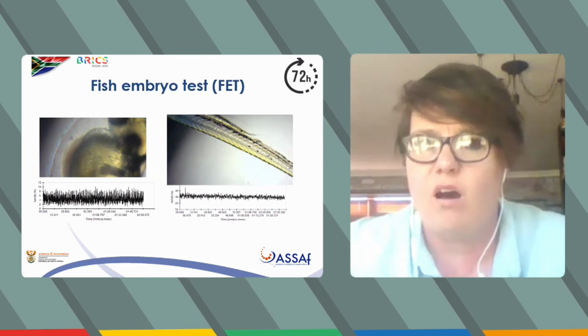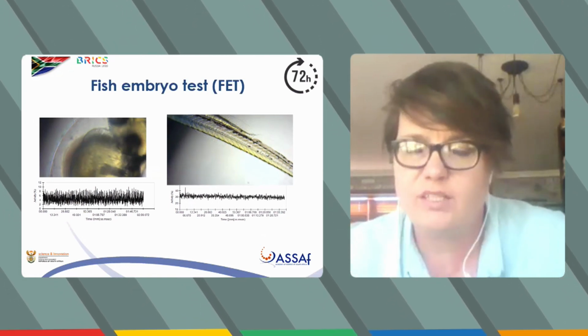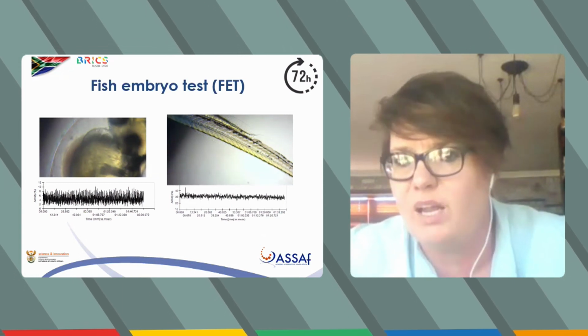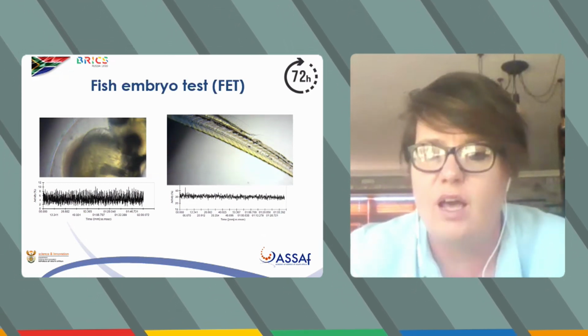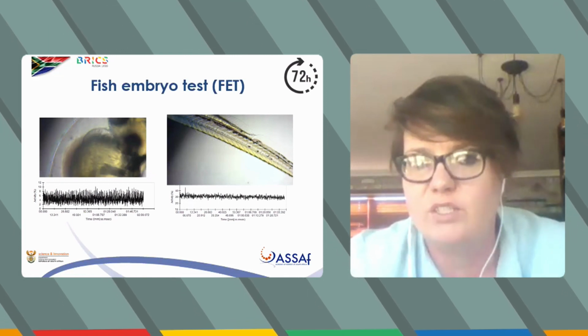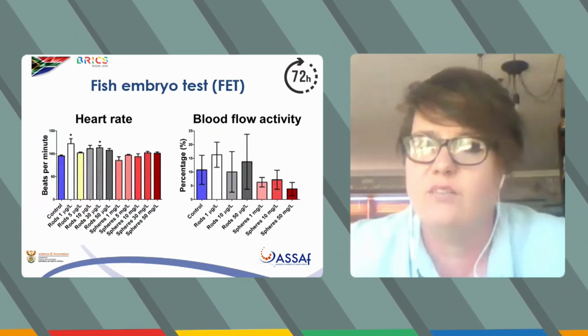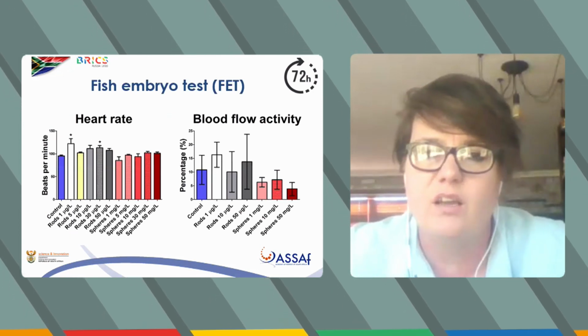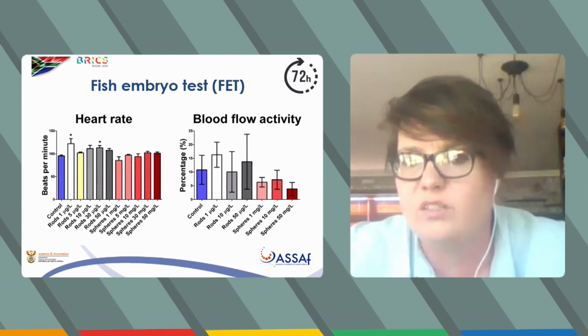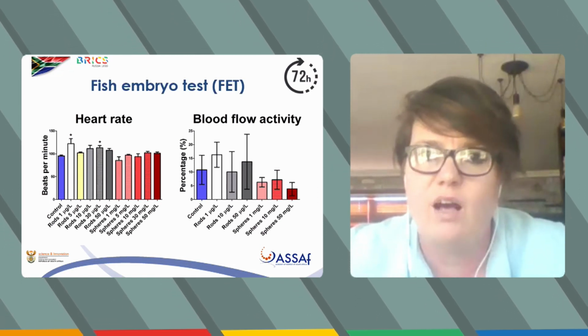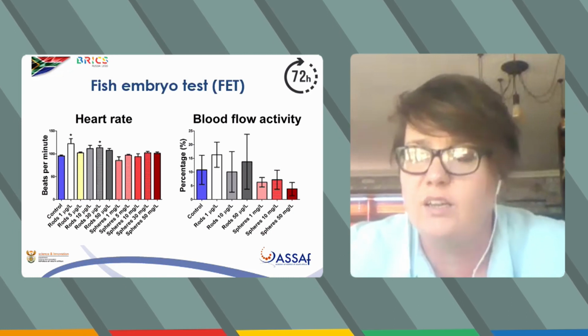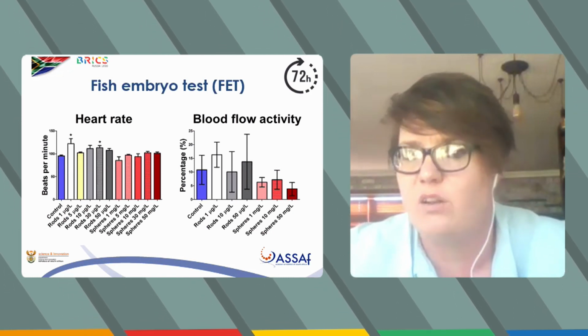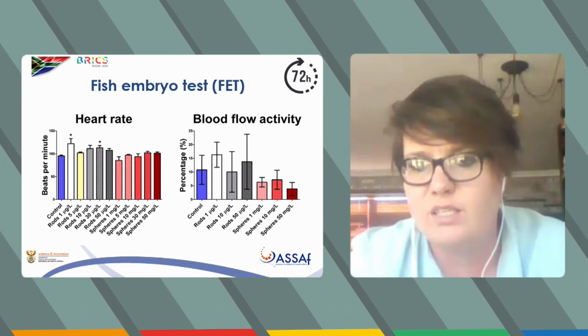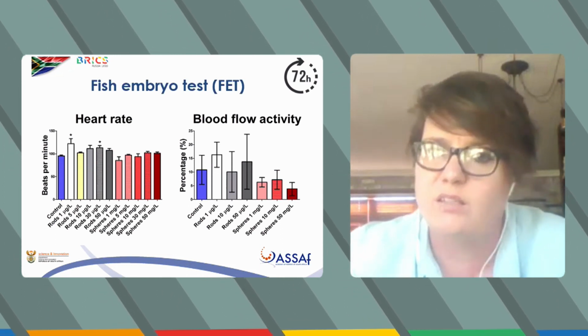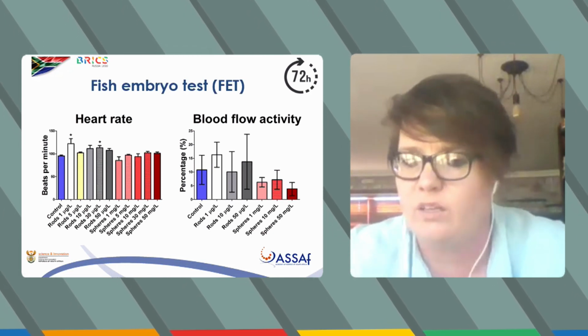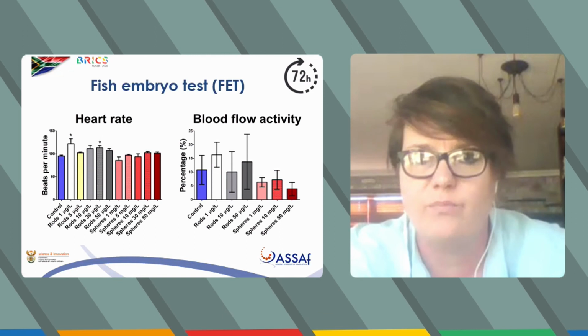When we look at the heart rate of the fish, the image on the left, you can see the heart beating, and on the right, you'll see the blood flowing through the caudal region of the fish. And what we then do is we measure the activity of these pixel changes, and this then gives us the heart rate and blood flow activity. With the spheres group, we did not notice any significant changes within heart rate. However, with the rods group, we did see a significant increase, and this is directly linked to physiological stress. The blood flow activity is very broad spectrum still, and admittedly, we will need to do several more replicates in order to get that error down.